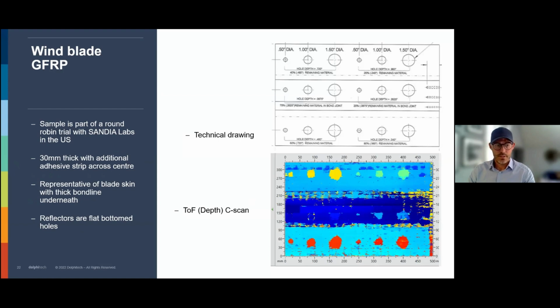So this is 30 to 35 millimeters thick, which is glass fiber and has more sound attenuation. So we have to go down in frequency to be able to inspect that. And as you can see, the resolution is not as good as high quality space or aerospace, but we can easily detect up to 2 inches of glass fiber as well.